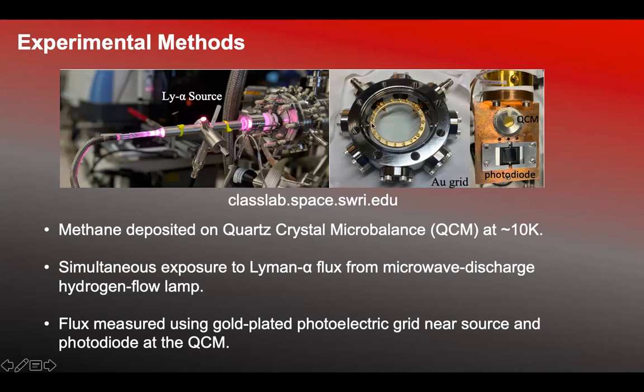So in the earlier experiments, we actually used a gold-coated wire grid to measure the flux of the incoming radiation, but the problem is that that's a very rough way of going about doing it. We updated it with a photodiode later, but there are actually some other challenges with photodiodes. So we've had to do a little bit of work interpolating what the actual intensity of the Lyman alpha band is here, which is my contribution to this particular project. I'm going to be a co-author on a couple of papers that have to do with this work. And I help to basically constrain what that Lyman alpha band radiation is.